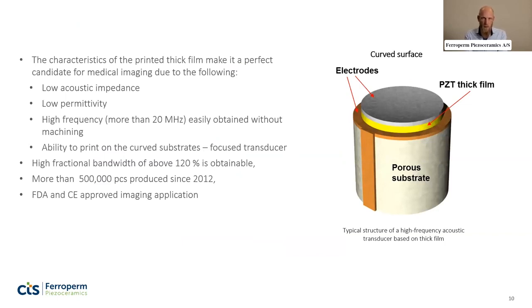So I'll talk a little bit about one of the more successful applications that we have where we've been using thick film. This is high frequency imaging. So the device that you're seeing here is a device with a thick film pad printed on a curved surface of a porous ceramic substrate. And this is done by pad printing.